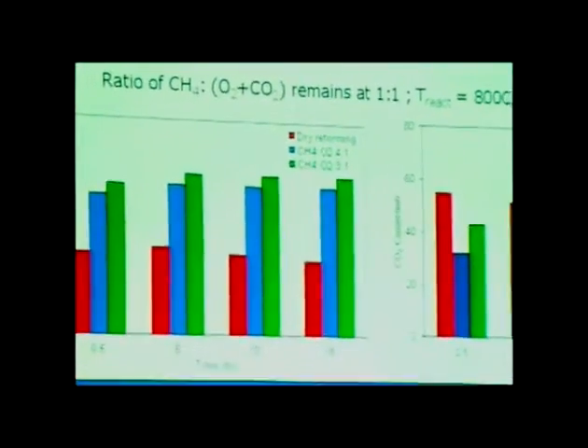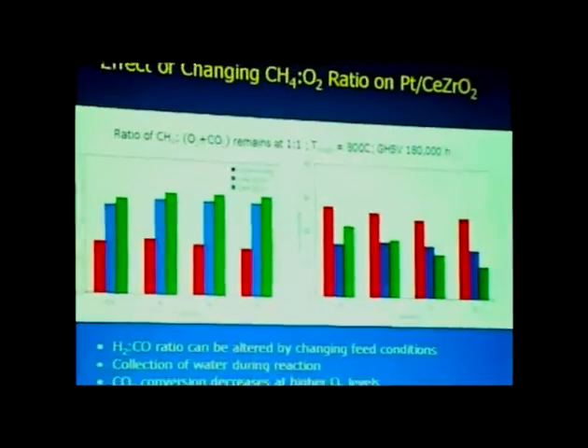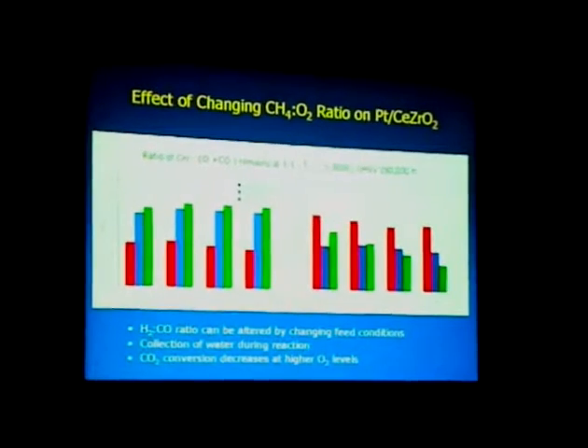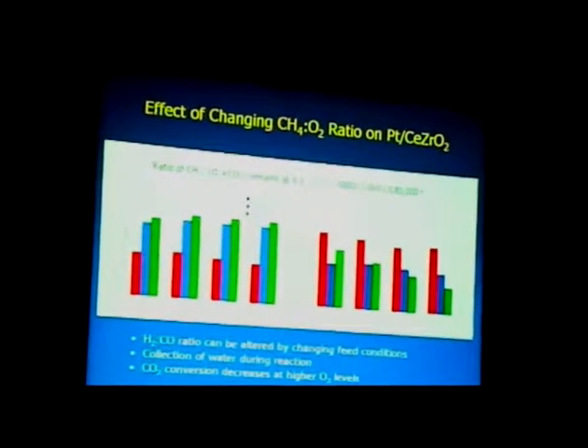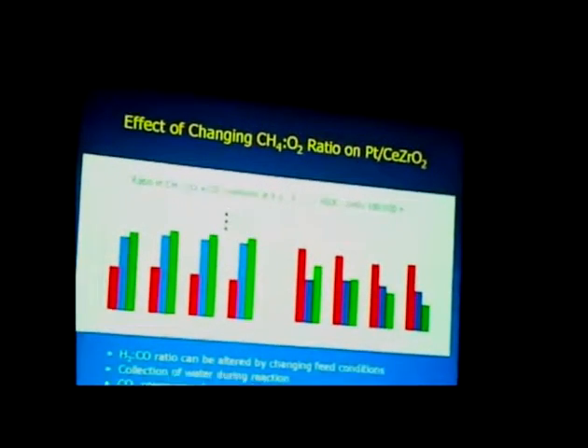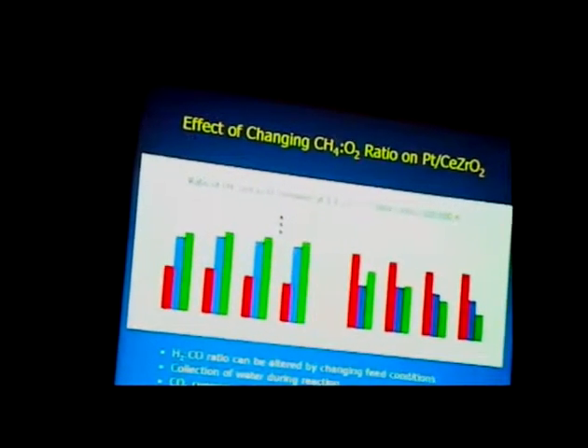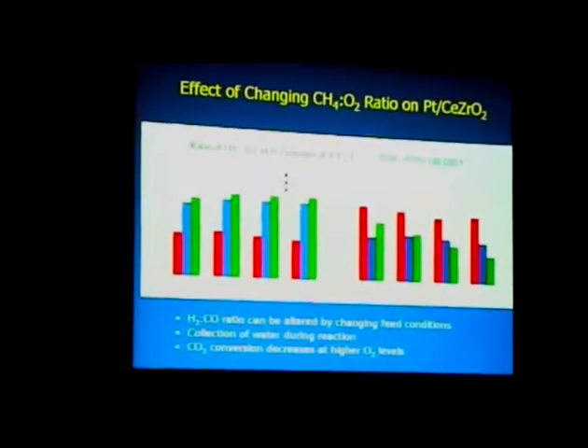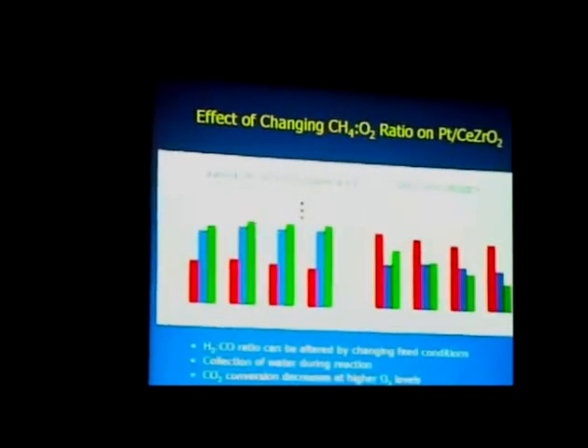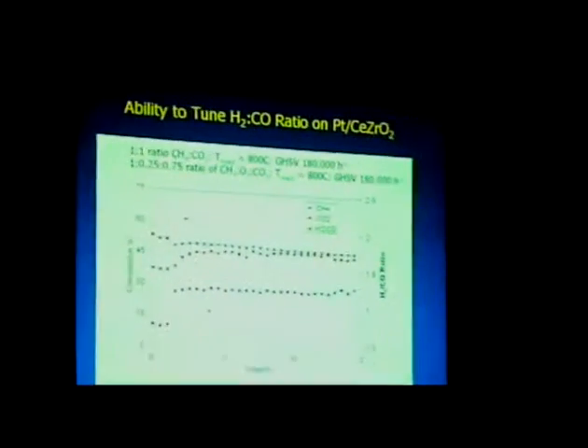decrease here in your CO2 conversion, and in some cases, if you let it go for a long time, you can actually see CO2 production. And what's happening is you're basically having methane plus oxygen going to CO2 and water. So as your concentration of oxygen gets really high, you're basically forming your combustion products. And we do have a significant amount of water collected during the experiment.